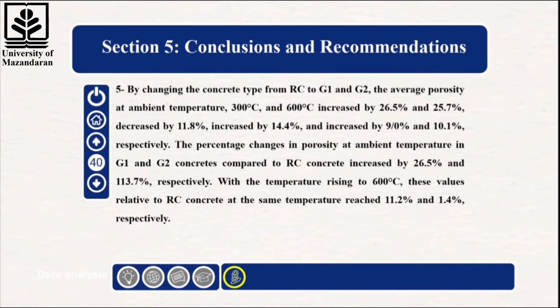5. By changing the concrete type from RC to G1 and G2, the average porosity at ambient, 300 degrees Celsius and 600 degrees Celsius increased by 26.5% and 25.7%, decreased by 11.8% and increased by 14.4%, and increased by 9% and 10.1%, respectively. At ambient temperature, porosity in G1 and G2 was 26.5% and 113.7% higher than RC, respectively. When the temperature increased to 600 degrees Celsius, these values compared with RC at the same temperature were 11.2% and 1.4%, respectively.